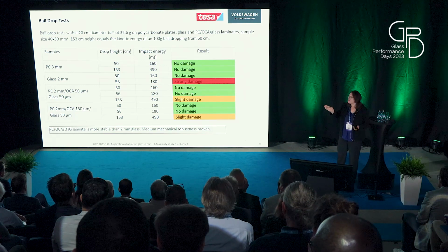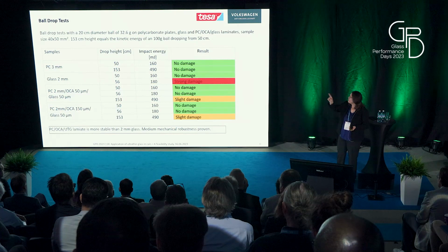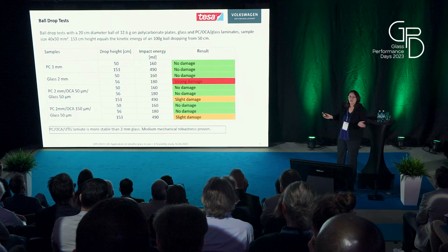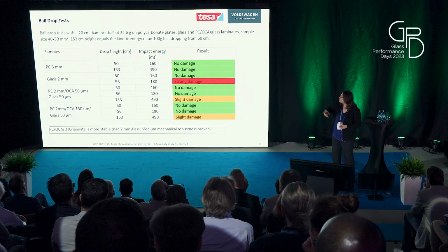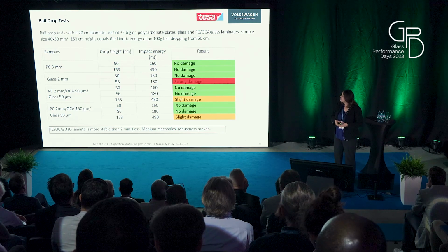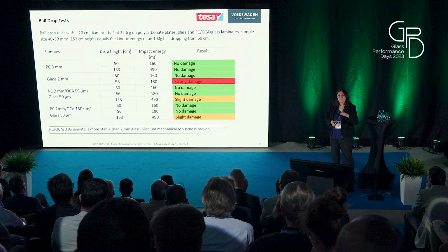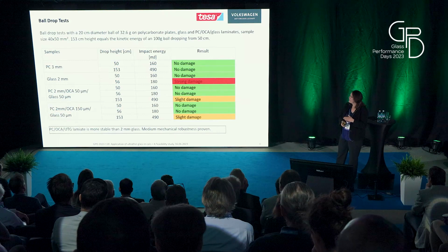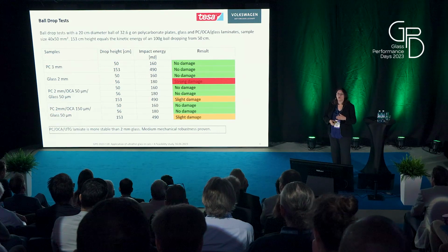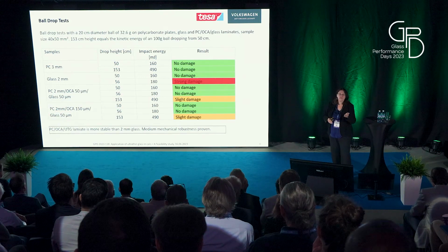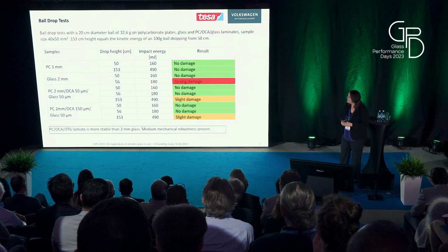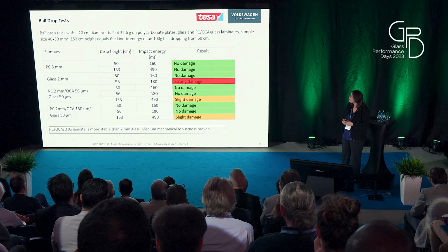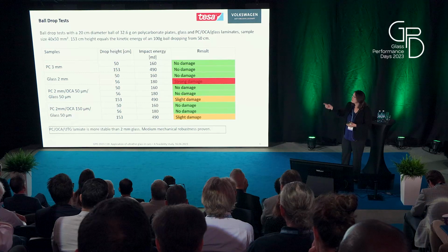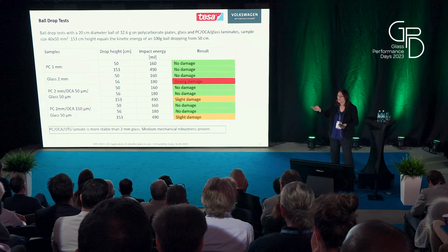The kinetic energy is the same, and you see if you go for polycarbonate, it survives all of the heights, so up to 1.5 meters. If you just take untempered glass, it already breaks at 56 centimeters, so it's not so stable. I mean, if you temper it, it's better, of course, or if you make it thicker. And if you go for the laminate, you see it's far stronger than just pure glass.